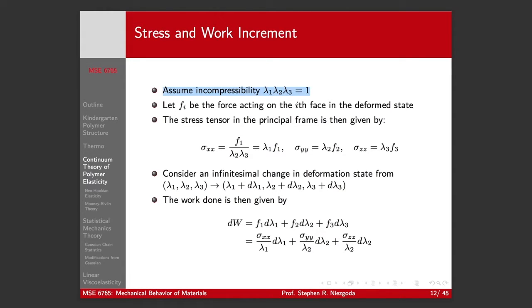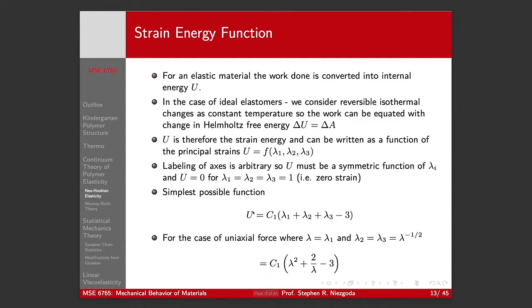And if we consider an infinitesimal change in deformation state, we add a very small change to our stretch ratios. We can come up with the work done in our system as given by this. Our increment in work is f one d lambda one, plus f two d lambda two, plus f three d lambda three, or stress divided by the stretch ratio.